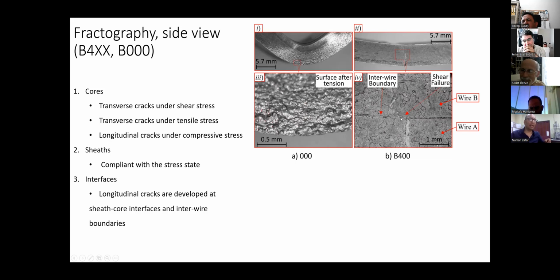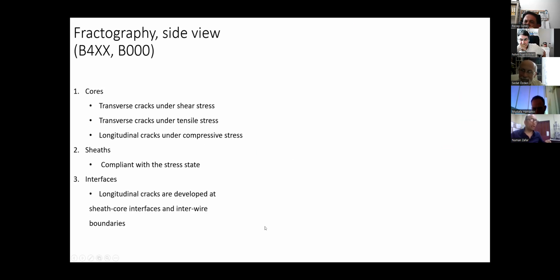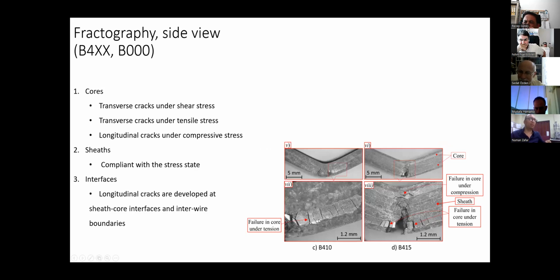And we can see that the cracks which are formed in the transverse direction, when they reach the interwire boundaries, they tend to change instead of being transverse to the longitudinal direction. So after these observations, I have taken these notes. Cores are preferably failing with the transverse cracks, no matter if they are under tension or under shear. That means that the cores which belong to the wires of the material fail in transverse cracks.